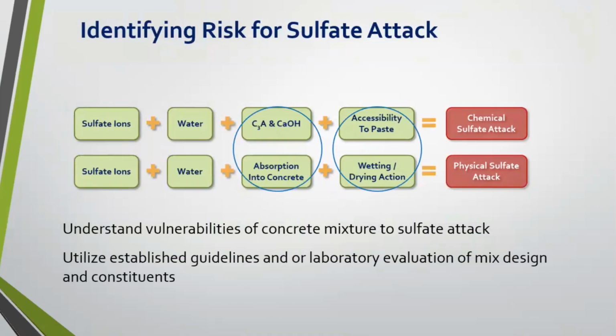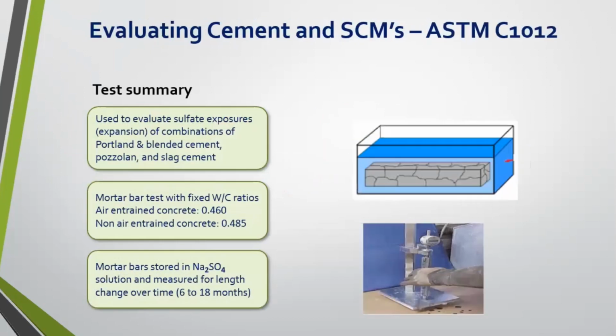So we're understanding the vulnerabilities of the concrete mixture to sulfate attack. So now we have to utilize the established guidelines and or laboratory evaluation when we're considering what constituents we're going to use and what that mix design is going to look like. So the primary test for evaluating cement and SCMs for this is ASTM C1012. You may or may not be familiar with this, but it's a lengthy test, and it's used to evaluate sulfate exposures and the corresponding expansion of combinations of Portland and blended cements, pozzolans, and slag cements.